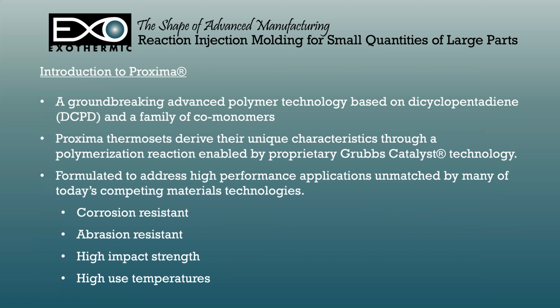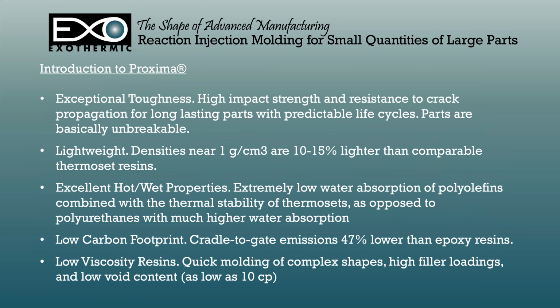So when you take a look at this material versus others, you have excellent corrosion resistance, and it approaches the corrosion resistance of the fluoropolymers like PVDF, which is very good. It's very abrasion resistant. You have extremely high impact strength. It can also almost be used as a ballistic material, and you have high use temperatures. So again, it has exceptional toughness, high impact strength, and resistance to crack propagation for long-lasting parts with predictable life cycles. Parts are basically unbreakable, and this is important. They don't fail by cracking. It's a very tough material.